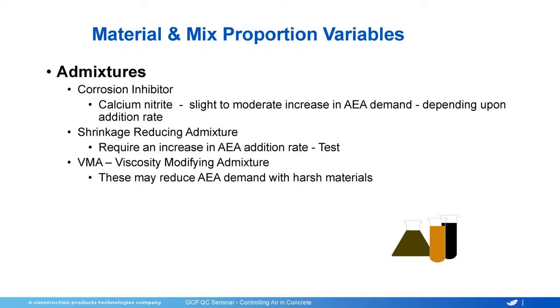Viscosity modifiers can be your friend if you're struggling to get air, especially if you're placing high slump mixes or high flow mixes, and you're having what I would say is a bit of a witch's brew. So you place the concrete in the forms, or you place it in a bucket to deliver it, or you see it in the truck and you get that bubbling cauldron effect. Doesn't necessarily mean all the air is coming out, but it does mean that mix is struggling to maintain its stability. And you will see those mixes tend to be much more difficult to keep the air.